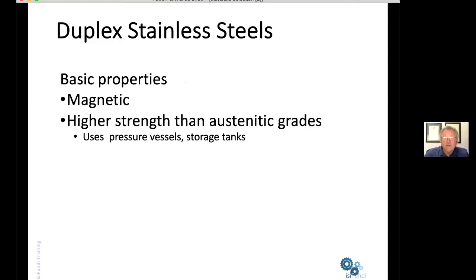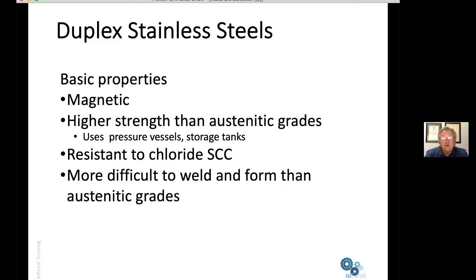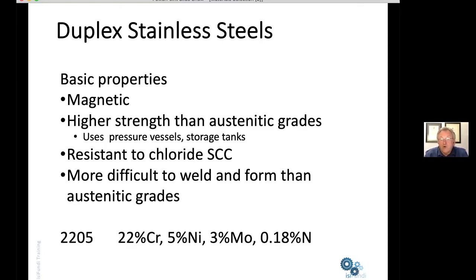So now take a duplex stainless. This is a combination of ferrite and austenite, and although they're a little bit more difficult to weld than the austenitic materials, they are now resistant to the chloride stress cracking problem, and they have weldability characteristics that are closer to the ferritic steels. One of the more common materials that you may have heard about is one of the proprietary alloys, I think it's from Sandvik, SAF 2205, 22% chrome, 5% nickel, and this gives us the duplex metallurgical structure.